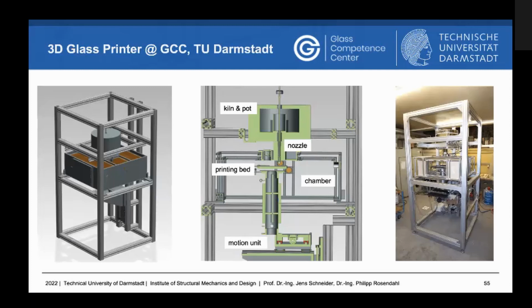Unfortunately, I can't show printed samples, but the basic structure is that we have a cavity in the top of the printer that will melt the glass, will extrude it through a nozzle, and then have a heated chamber. This is the heated chamber. You can see it on this side too, where we can control the temperature on the base plate that we're printing on to have a connection at the desired temperature between the melt and the base plate, and of course a motion unit that translates and rotates our sample.